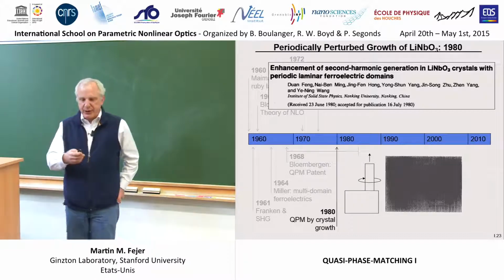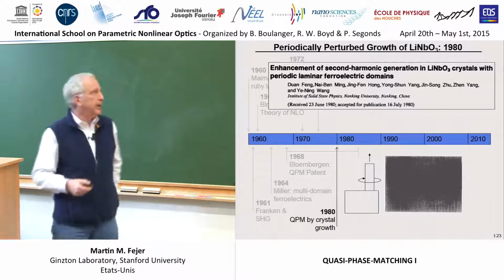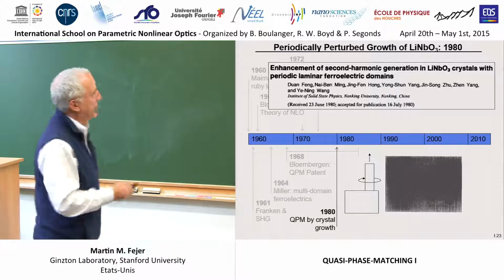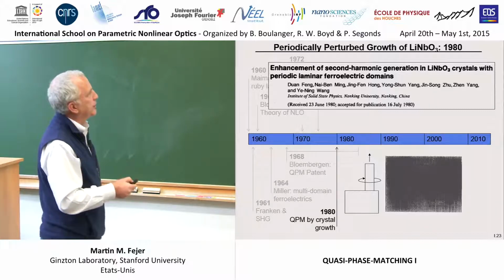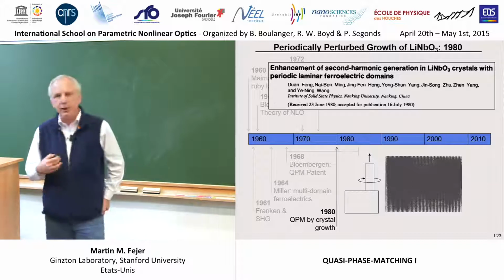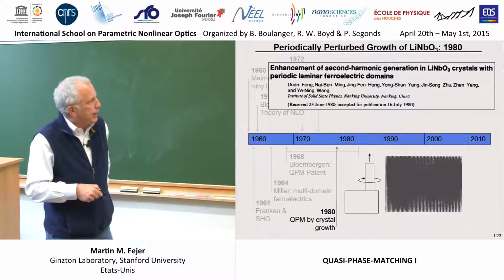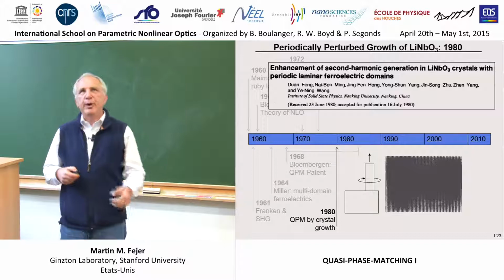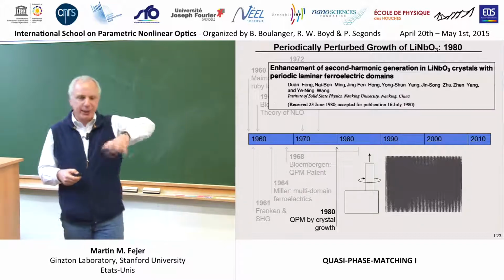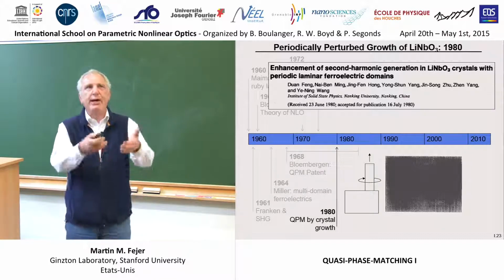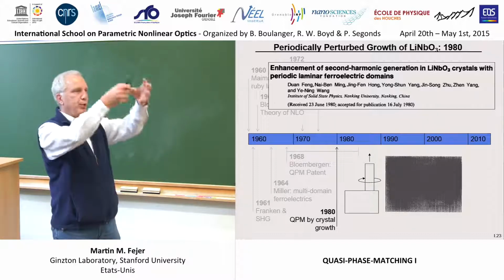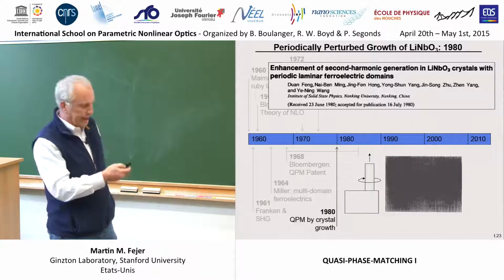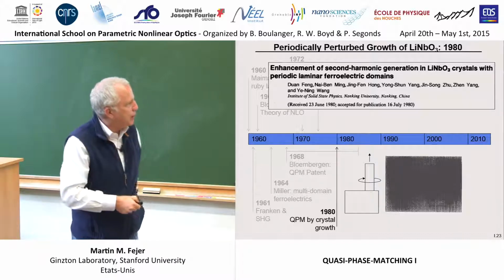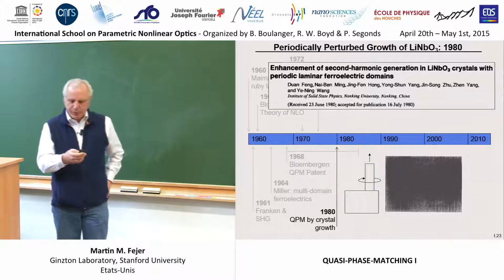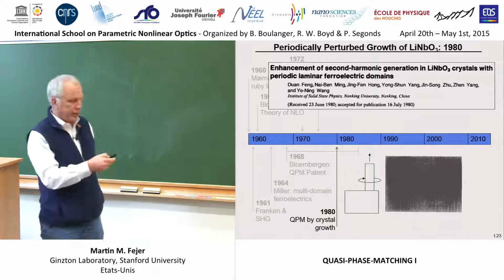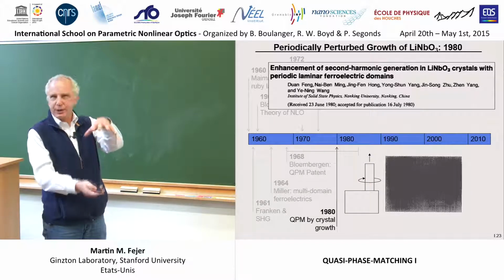The first monolithic scheme I'm aware of was done by Nai-Ben Ming and Feng in Nanjing University. They grew a crystal of lithium niobate from a melt. They rotated it eccentrically in the melt, so the growth rate was periodically perturbed. And with a constant pull rate and a periodic perturbation, they were able to induce domains to form periodically in the crystal, though of course you can imagine that this big convecting melt is a difficult thing to